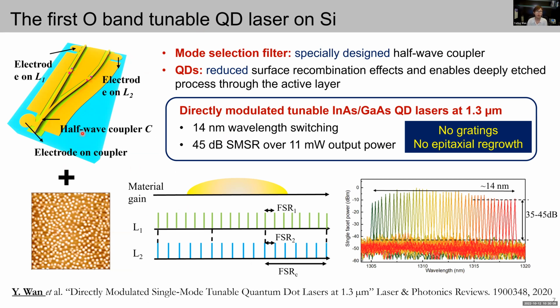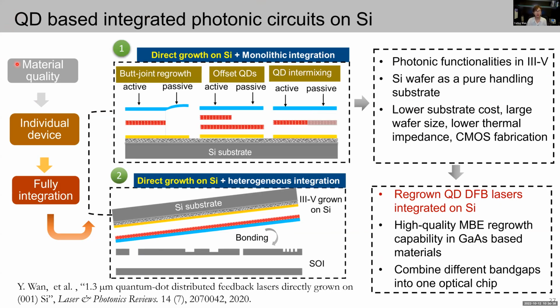And with this simple and integrable device structure, without using any grating lithography or regrowth process, we demonstrate the first tunable single wavelength quantum dot laser, where these two Fabry-Perot cavities have slightly different lengths to shape the Vernier spectrum for wavelength tuning. And we got 14 nanometer wavelength spacing with up to 45 dB side-mode suppression ratio over 11 milliwatt output power. So in addition to the material quality and individual quantum dot device performance, a lot of effort is also needed to form fully integrated photonic integrated circuits.